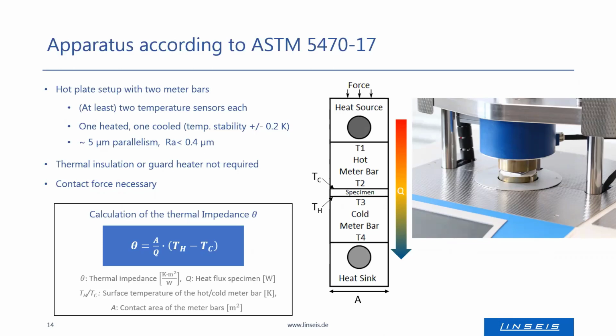The thermal impedance is then calculated according to this formula, where the contact area is divided by the average heat flow through the stack and multiplied with the temperature difference between the hot and the cold surface, so the hot and the cold meter bar.